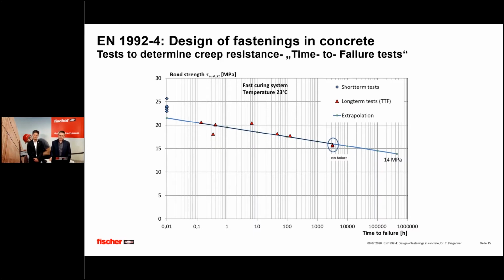And with doing so and putting these results of time to failure tests in a diagram, as it is shown here, you see on the y-axis the bond strength, and on the x-axis the time to failure in the logarithmic scale. Then you see that this transferable bond strength in time to failure tests, in creep tests, in tests with a constant tension load on the anchor, decreases relatively fast with increasing time to failure. These are the red triangles in my graph. These are the result of time to failure tests, where the blue diamonds are results of the short-term tests.